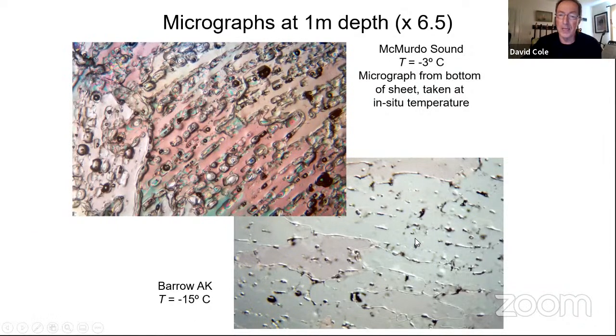Drop it down to -15, and we see this very much close off of all our brine inclusions, just because of the equilibrium conditions for brine in the ice matrix. This process is kind of interesting to look at. It turns out that there's some things going on with the influence of this aspect of the ice matrix as a function of temperature on the overall elasticity of the ice that I'll talk about in a second here.